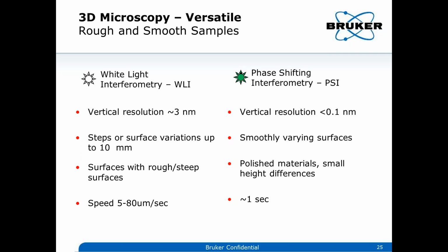The white light technique can measure rough samples and steep samples. The PSI technique is mainly designed for polished material with very low height variations. The speed for white light interferometry can vary from 5 to 80 microns per second. That's how fast you can move your objective in Z, whereas in PSI it's a second or two. You can quickly change the phase of the incident light, so it's very fast.